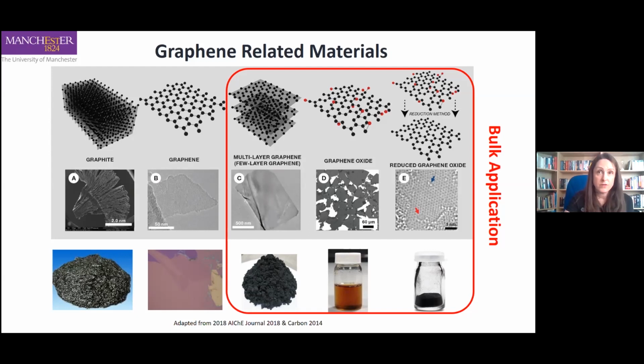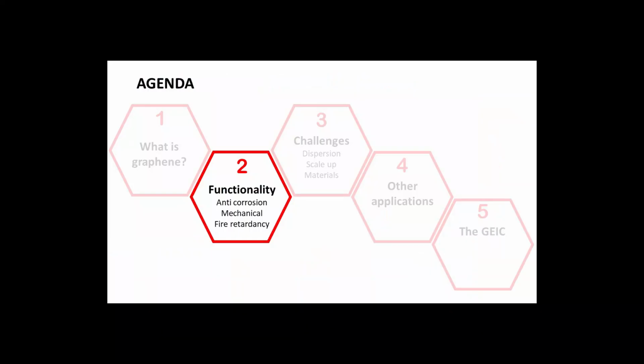Finally, on the right, we've got reduced graphene oxide. And as the name suggests, that's graphene oxide where we've taken away those functional groups, and we've reduced it back down. And there's lots of reasons why we would take that route to get graphene-based materials. Very often it's easier to use graphene oxide and then reduce it than to try and do the same thing using graphene straight away. But I won't go into too much detail about that just now.